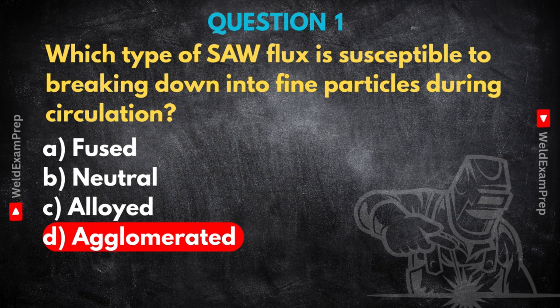And why is that a problem? Well, too many fines can mess things up. It can affect arc stability, leading to defects like porosity or maybe inclusions. Right, things an inspector definitely doesn't want to see. Definitely not. It can also make the slag harder to remove after welding, and in some cases, it might even subtly change the weld chemistry if some of the finer, crucial elements get lost or unevenly distributed. Okay, so it can compromise the final weld properties. Potentially, yes. So it's about being proactive, checking that flux condition, not just assuming it's okay. Got it. A vital check for consistent quality.